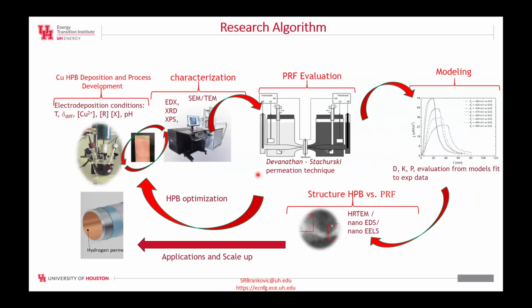All right, so our research is basically having several stages. We are, first, working in a laboratory on a beaker level where we develop coatings and test them and look at the structure, and then we evaluate a little bit larger coupons for permeation reduction factor using the Devanathan-Stachurski cell. And then we model the transients from these experiments to also extract diffusivity, solubility, permeability of the hydrogen in this double layer membrane type of structures. We also look into the grain analysis, grain boundaries to learn what really affects the best or reduces the best hydrogen diffusivity and permeation through this membrane. And then we go back, even improve further, and eventually look how to scale this up to a real pipe geometry.